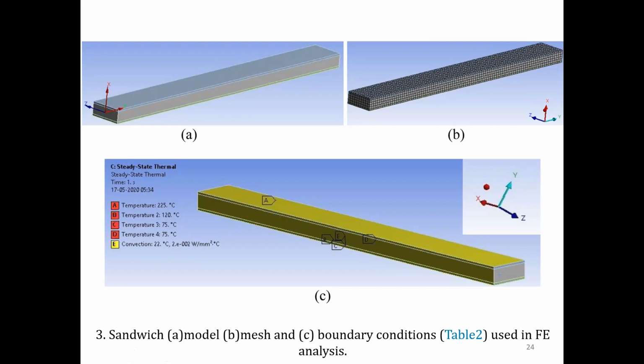We manufactured these sandwiches, what you can see here, having a core of 20% glass microballoon infused high density polyethylene, then 40, then 60, and we named it as SH, S for sandwich, H for HDPE. So SH20 means 20% of glass microballoons by volume in HDPE matrix and the sandwich of it. If I say H20, it is only the core. And if I say SH20, it is the sandwich made up of the H20 core. And that is how you will see the naming done in the subsequent slides.